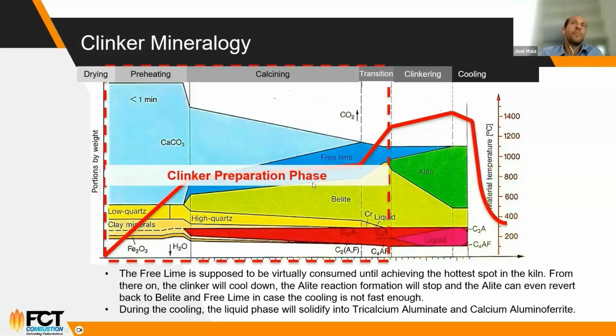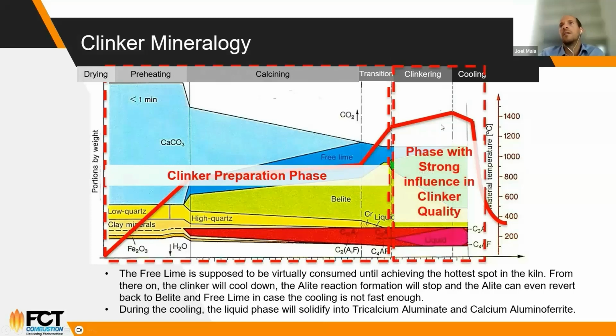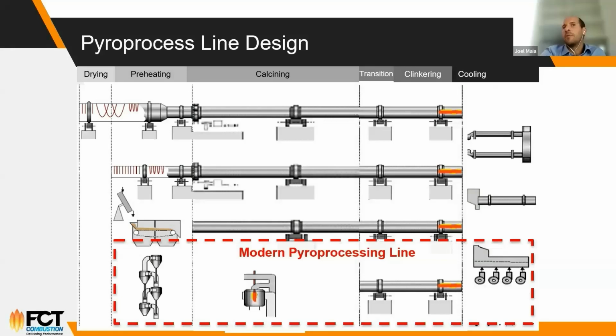One phase where you are preparing the clinker, so you start with the final drying, then you preheat the material, you start calcining it, and then you come to the transition zone. And then a second phase, where what you are doing has a very strong influence on the clinker quality. So we have to differentiate these 2 parts because this will influence how we can burn alternative fuel in the preparation phase and how we can burn alternative fuel in the clinkerization phase.